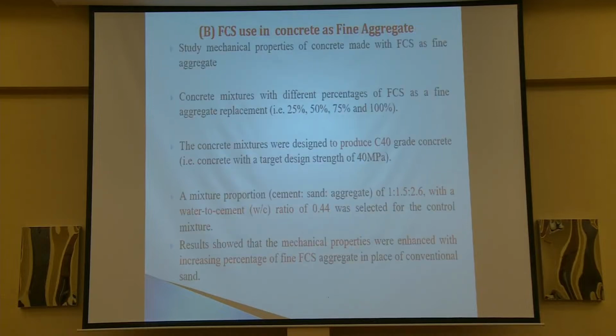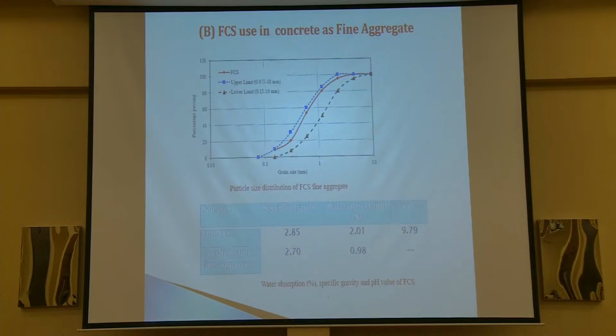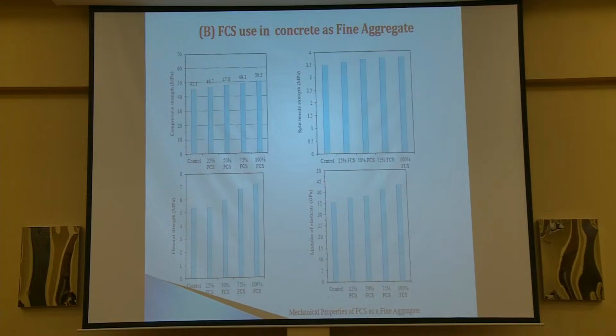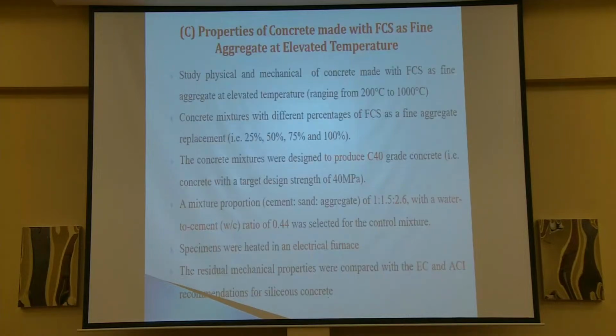So then we studied the use of ferrochrome slag in concrete, and we find that this is the grading, and this is the comparison between the lower limit and the upper limit. And we find that there is good improvement also and reduction in the shrinkage, and there is good improvement in the compressive strength of concrete, and also in the modulus of elasticity.